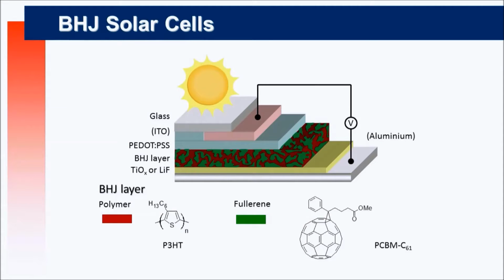So how does it work? Of course, if you're dealing with solar cells, you need one electrode which is transparent, or at least semi-transparent. Most of the time it's based on ITO. It could be carbon nanotubes or nanowires of silver. There are new potentials there. But most of the time it's ITO on glass, which is quite cheap. And ITO on plastic, if you want it flexible, is much more expensive. It's a totally different technique. And you need a counter electrode, could be printed aluminum, printed silver.